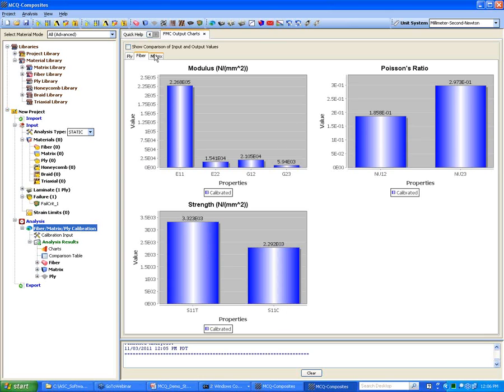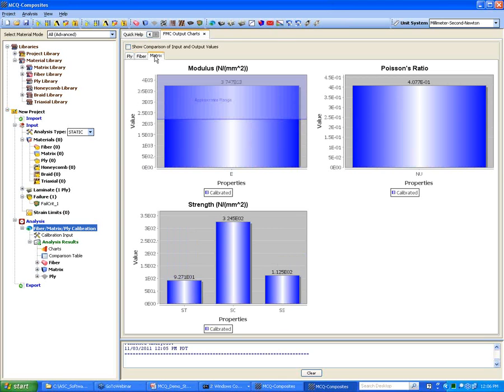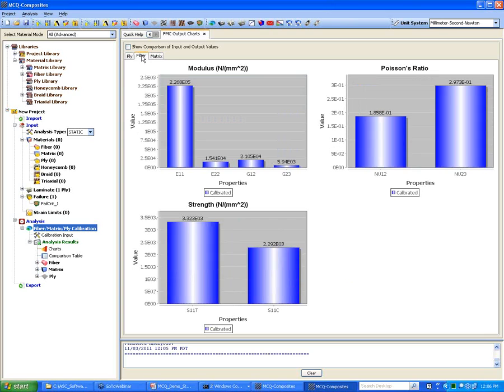These are approximate values that are reverse engineered accounting for any thermal residual effects, so they are slightly different from bulk properties. Similarly, you can click on Matrix and it reverse engineers the matrix modulus, Poisson ratio, and strength values, assuming an isotropic matrix. Fiber is assumed transversely isotropic unless you choose glass fiber, which is assumed isotropic.